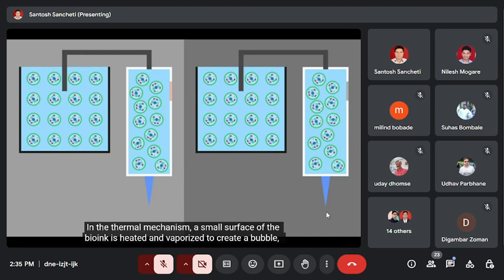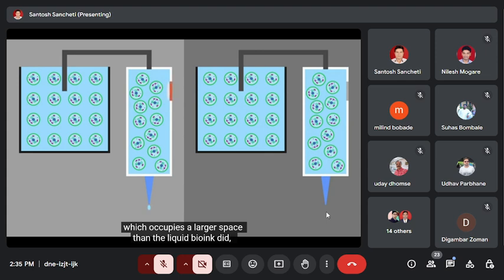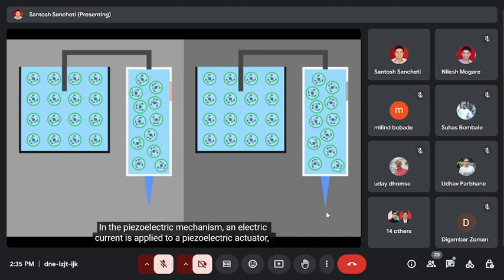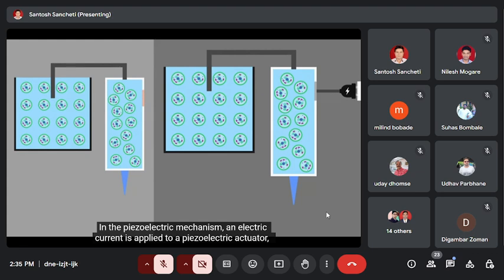In the thermal mechanism, a small surface of the bioink is heated and vaporized to create a bubble, which occupies a larger space than the liquid bioink did, creating pressure, forcing a droplet of bioink out of the nozzle. Once the bubble collapses, a bit of bioink is sucked from the reservoir, refilling the chamber, and the process is repeated. In the piezoelectric mechanism, an electric current is applied to a piezoelectric actuator, causing the chamber to deform slightly, forcing a droplet of bioink out of the nozzle.